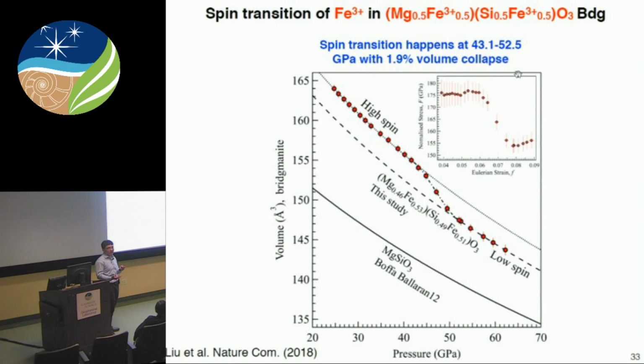Secondly, as we saw before, the synthesis from akimotoite to perovskite, or Bridgmanite, doesn't require heat. Heating can always cause some problems, like chemical diffusion and valence redox reactions. But in our sample, we don't use any heating, so the data are as clean as possible. And thirdly, we have about 10 times more iron content than the normal Bridgmanite composition, so any influence of the spin state could be clearer. It's beyond the experimental uncertainties.